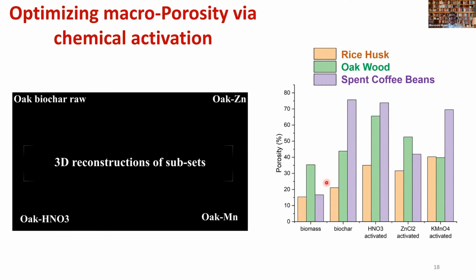So this is the biomass, and tomography was done on these pure biomasses without any carbonization first, and you see that they have lower macroporosity. Of course, when we are using microtomography, we are not actually measuring microporosity, we're measuring macroporosity, because the resolution that we used was more on the order of 0.1 to 0.3 microns. And then you make biochar out of those, and then you have a very different kind of macroporosity.